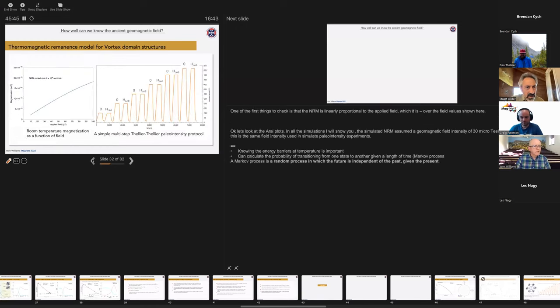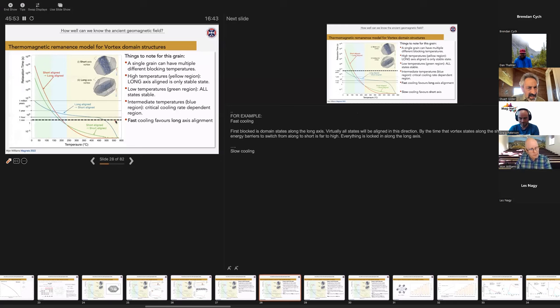So that's what I show here on the left-hand side, the sequence of temperature and fields as a function of time in our simulated multi-step Thellier experiment. This is just one protocol. Actually the simulations I'll show you will have PTRM checks in it and PTRM tail checks in it as well. So here's the first simulated Arai plot. It's for a slowly cooled NRM over 600 million seconds. So that's about 18 years. And as I already said, the laboratory cooling rate of 40 minutes. This slow cooling has resulted in domain states predominantly aligned on the short grain axis, and the fast laboratory remagnetization realigns the magnetization to the long axis. So the large difference in the remagnetization occupancy of states results in this very large PTRM check failures shown by these red triangles here.